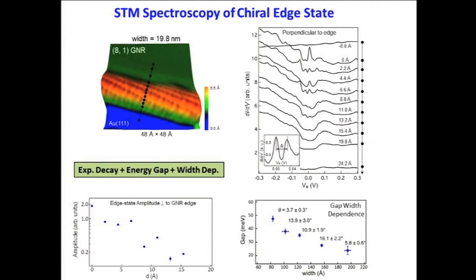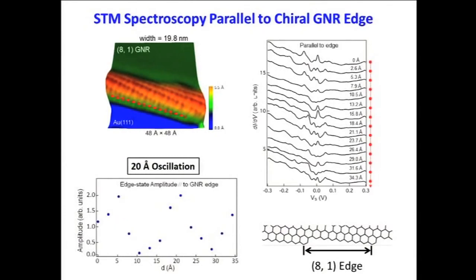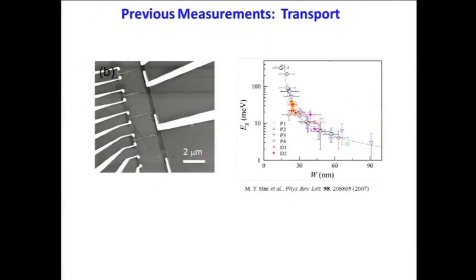Now, we measured how the edge state varies parallel to the edge, and in this data we see that the amplitude of the edge state oscillates. It goes up and down and up and down and up. So there's a periodicity to the amplitude of the edge state, which is approximately the same periodicity of this 8-1 edge. So now we have the atomic scale structure and the electronic structure of the edge.